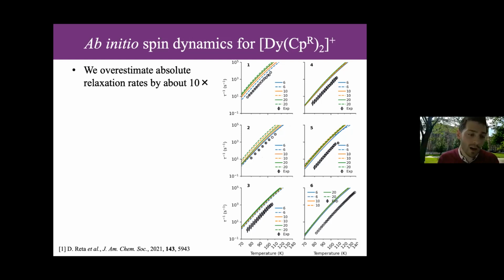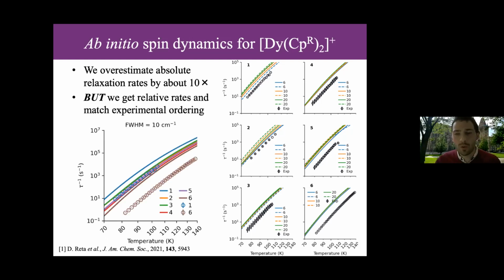There are so many approximations we make in this method. It could be any one of them. And we are systematically working our way through to try and understand why, but we don't have an answer as yet. So while we do overestimate things by a factor of 10, you could say that's terrible. But if you think about it in terms of a completely ab initio approach, that's not bad as far as I would be concerned, because consider that your rates are changing by many orders of magnitude as a function of temperature, and we're only off by sort of 1. So it's a small shift on the scale of things.